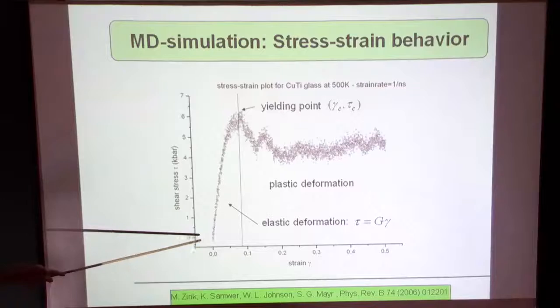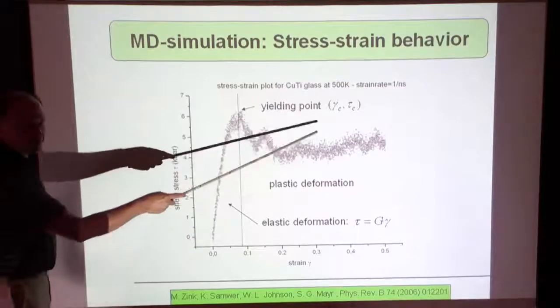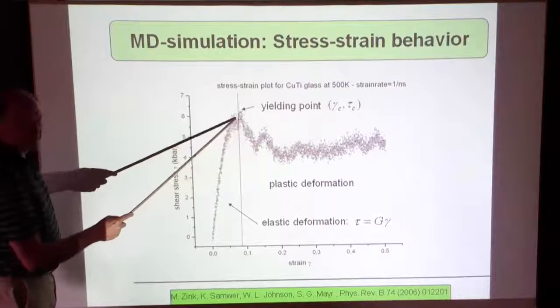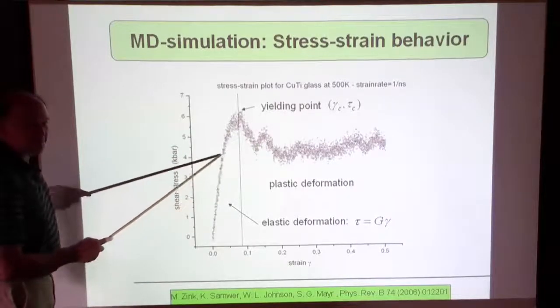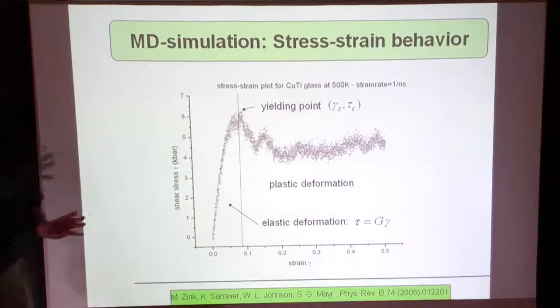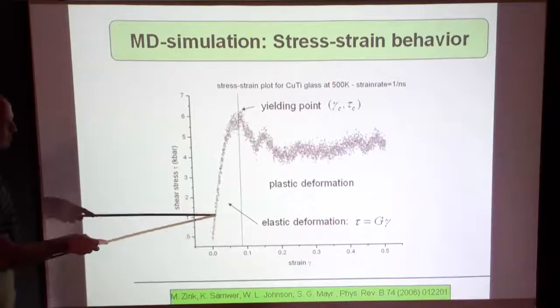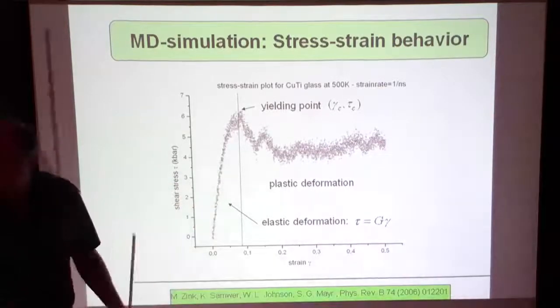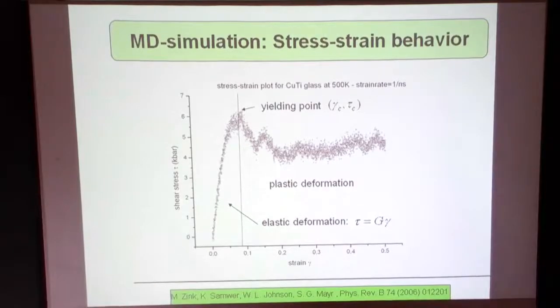This is MD again. We are not in the regime of serrated flow after the yield point. We are in this region here. So it's not true that there is really an elastic material. Even down here, at very low stresses, we already see jumps. Can you relate it to alpha to beta processes? That's an alpha process, which is the composite of the beta processes, as far as we can see, because we have a length change, and we can recover it to a certain amount. Not all of the jumps can be recovered. Okay, there is some plastic deformation also.